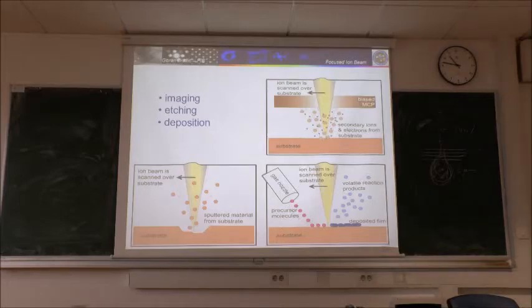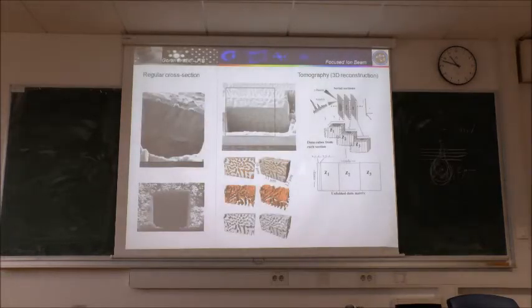Okay, how can we use this focused ion beam? There are three basic areas that we are using: imaging, etching, and deposition. Imaging we already described, what type of signals and what is the influence of different parameters on the signal. We use this multi-channel plate as a detector, and we image the surface. We can increase the current of the ion beam, and we can drill a hole. This is etching. We can deep etch the material, or we can put in some gas which decomposes under the beam into a metallic thin film, a deposited thin film, and these are just the volatile organic remainings of this reaction. Maybe just some examples of all these different areas.